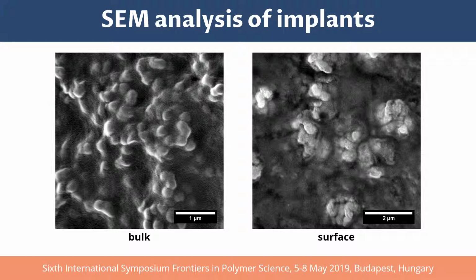Microstructure is more complex in the case of implants, but shows no indication of porosity. In the bulk, implants contain densely packed hydrogel-rich particles of submicron size dispersed throughout the hydrophobic polymer matrix. Near the surface of the implant, hydrogel-rich particles form small scattered clusters embedded in the hydrophobic polymer matrix, which indicates lower hydrogel content. This structure results from the so-called skinning effect, common in membrane synthesis by immersion precipitation. The surface region with lower hydrogel content can act as a diffusion barrier for drug release.